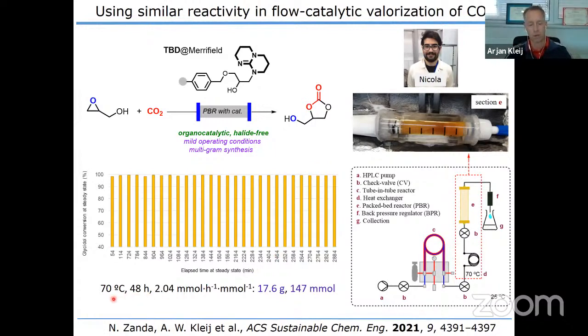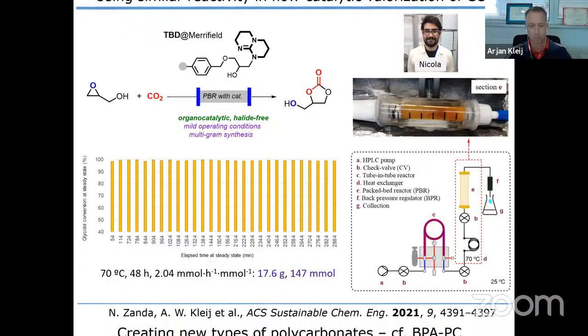Okay? So in this way, we did the reaction at 70 degrees during 48 hours with stable production of that glycerol carbonate, which gave us about 18 grams of that glycerol carbonate. And it shows very nicely that also this chemistry, substrate-induced CO2 conversion, can be translated to flow catalytic processes.